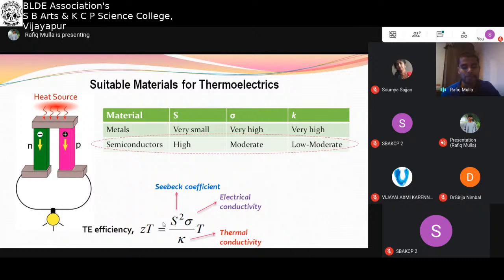How to evaluate ZT, from Tanjavur Govindraj. For ZT evaluation, again, you need to measure the Seebeck coefficient, measure electrical conductivity, and measure thermal conductivity of a material and put the values into this formula. Seebeck coefficient can be measured by applying a temperature gradient and measuring the voltage produced. So that is delta V by delta T. If you take delta V by delta T, that is nothing but the Seebeck coefficient. And you have well-known methods for electrical conductivity measurement: the 2-probe method and the 4-probe method. You can use any one of the methods to measure electrical conductivity of these materials.